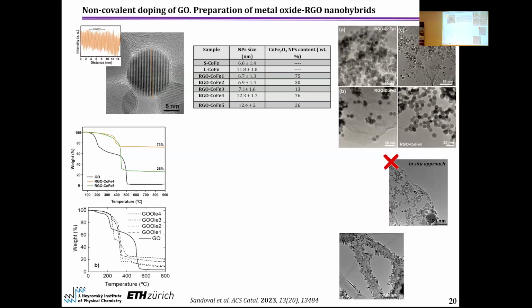One advantage of this technique is also that the presence of nanoparticles in the reactor induces the reduction of graphene oxide. That is usually one of the main issues of preparing samples with graphene oxide, because when you have samples which are not completely reduced, the electronic properties of the material change, and this can affect the application. So in this case, the presence of these metal oxides in the system also induces a very high reduction of the graphene oxide. So we can say that we have a properly reduced sample, and we only have particles attached and not other aliphatic groups. This is, for example, a comparison between the sample prepared by these methods, and this one is the sample prepared with oleate by microwave, and here we can see that we still have some aliphatic groups attached to the system.